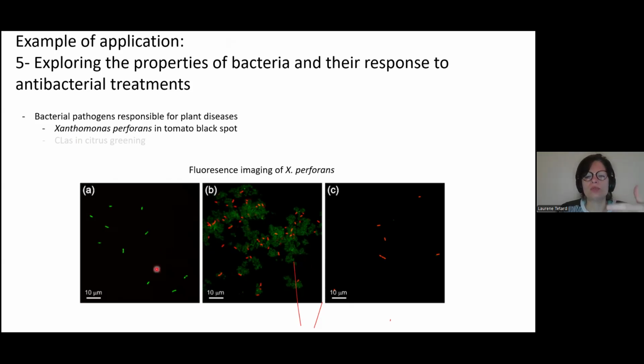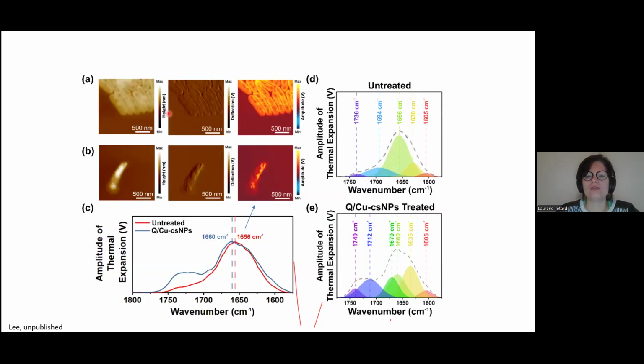So we developed a protocol to incubate bacteria with the treatments that were designed by his group. First, we did fluorescence mapping to see the live-dead assay and count how many cells survived the treatment under the conditions we were screening. But then we were interested in seeing what AFM-IR could do. So this is one picture that represents a little bit. We could find that the morphology of the untreated and treated bacteria is changing. The untreated bacteria are rod shaped and their morphology is pretty consistent from one cell to the other, whereas we could see some deformation and different parts of the bacteria forming after treatment.